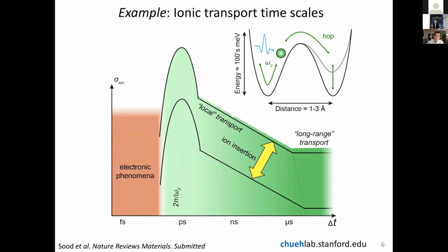And this is due to the fact that we have energetic barriers on the order of 100 or a few hundred millielectron volts and a hopping distance of 1 to a few angstroms. So ionic transport, just like phase separation, also spans a wide range of scale, in this case, time and length as well.